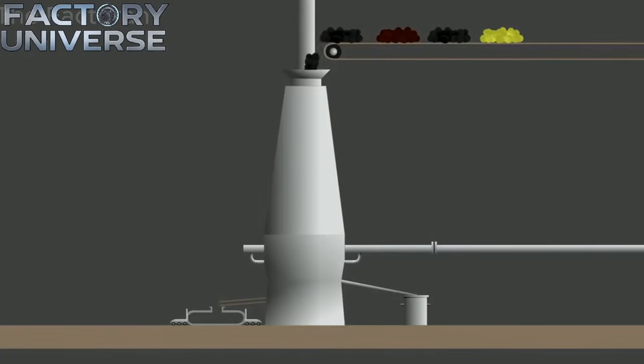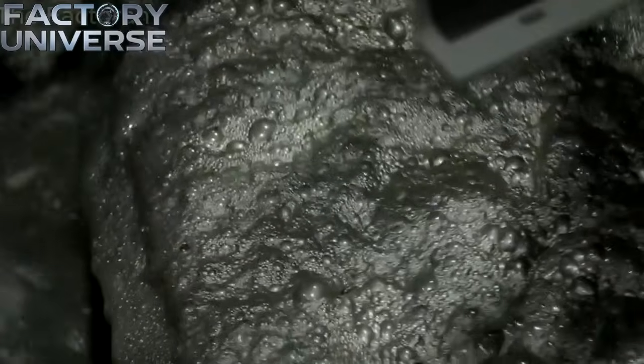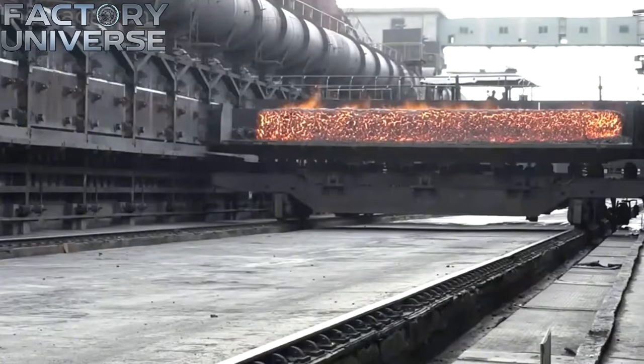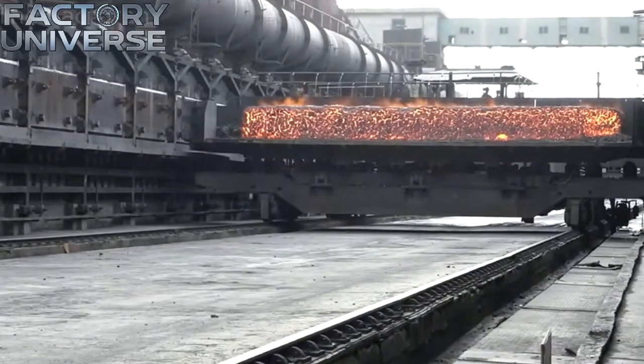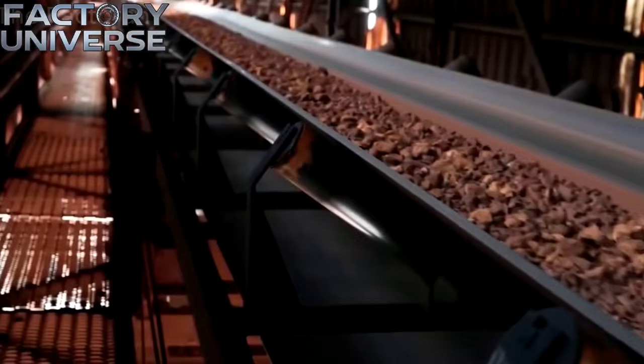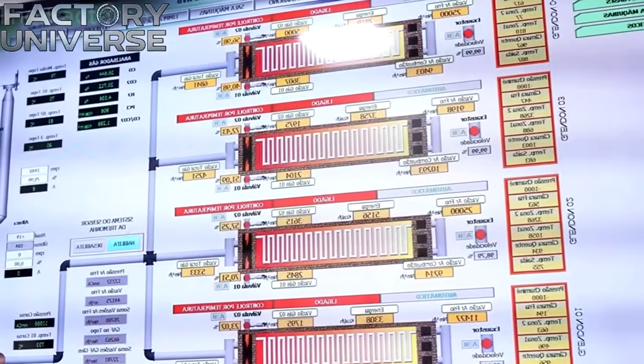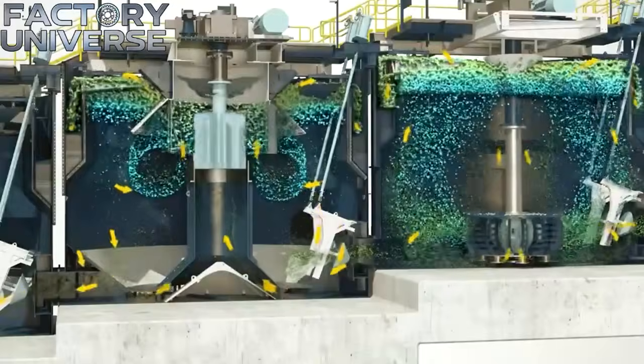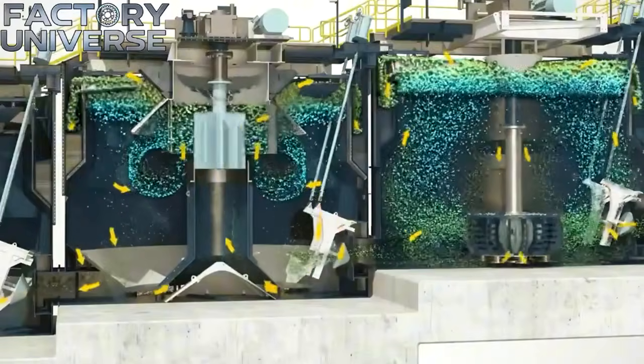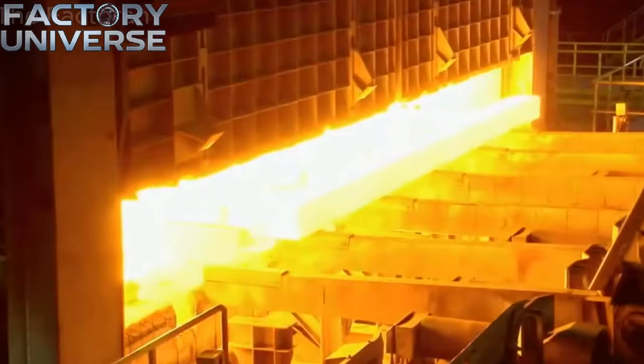It is visible how the equipment produces a concentrate with a metallic content more than twice that of the raw ore. After obtaining the concentrated ore from the flotation tanks, the next stage is filtration and dewatering. Vacuum filtration systems, typically drum or disc filters, receive the iron-rich slurry. Under the pull of pressure differentials, water is drawn out while the fine ore particles remain.